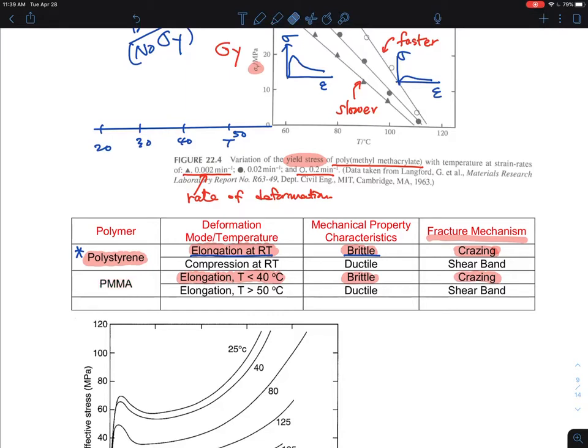On the contrary, if you're looking at the sample that is the case, where you are seeing some sample, polystyrene, for the same sample, if you do the compression of the polystyrene, you don't see the sample breaking. They are going to show some yield stress and the ductile deformation behavior. And the mechanism is called a shear band. And I'm going to show you what that is. And also the PMMA, particularly at elevated temperature, is something like 50 degrees or higher. They are going to do the ductile transition. And the mechanism that I'm going to say is a shear band. So this is a mechanism, a microscopic mechanism that we'll be discussing later in here.